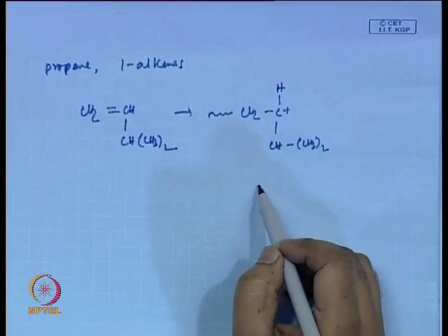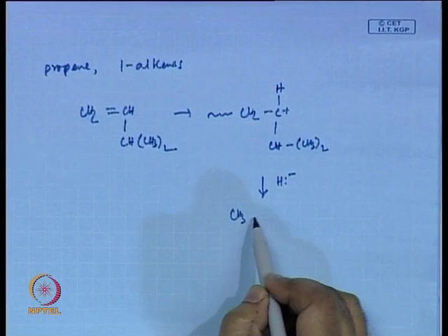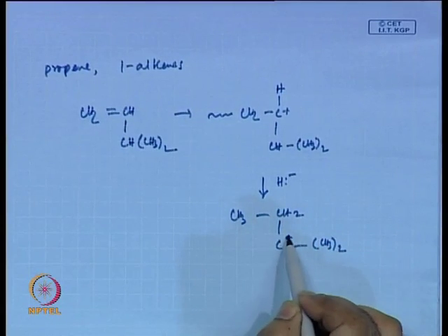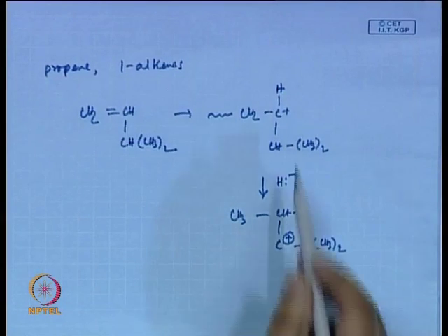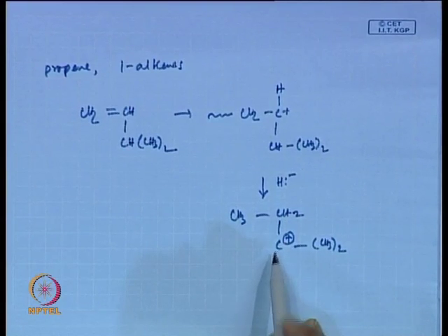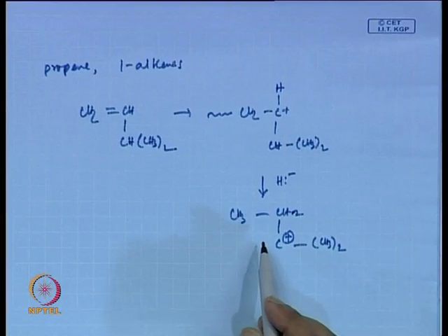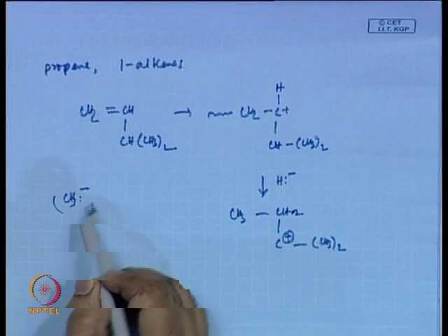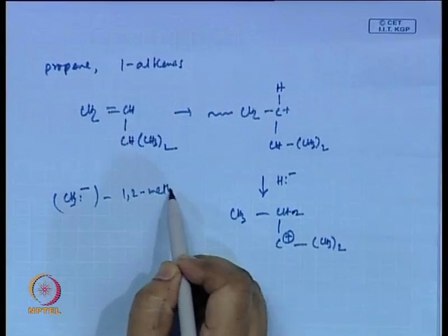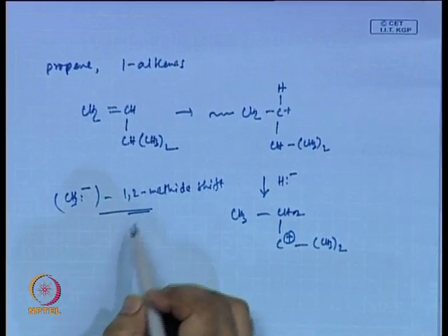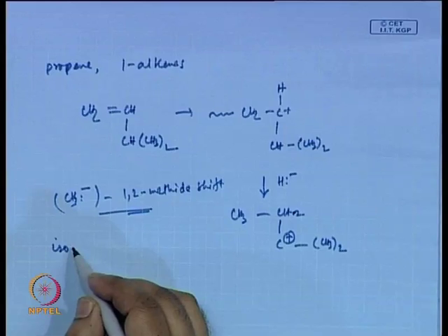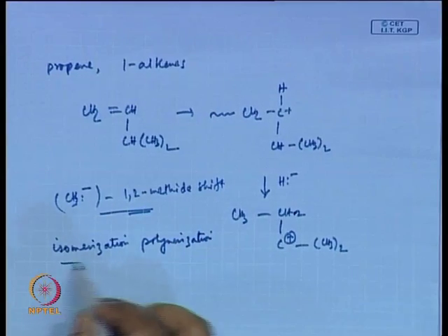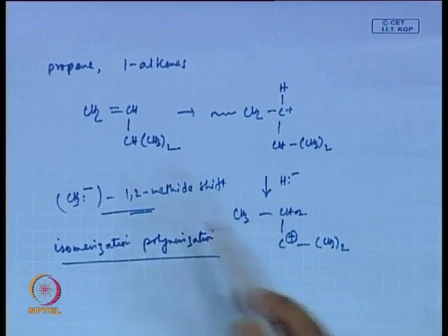Now, this carbocation can undergo a hydride shift. As a result, more complicated products actually form when there is this type of hydride shift, or in some cases a methide shift. If this happens, the reactions become very complicated, and we sometimes call that isomerization polymerization as well, but this is not common. This is applicable to some monomers, like the example we gave.